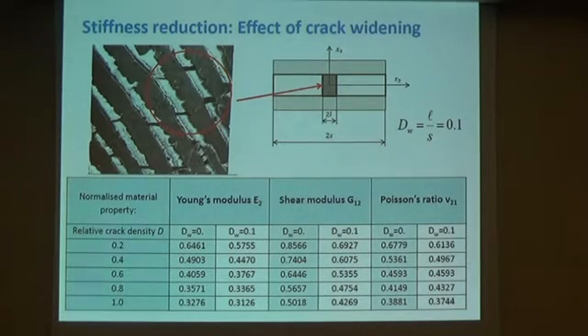How will crack widening contribute to stiffness reduction? Here is a reminder of the photograph with cracks in the ceramic layer, and these are cracks that are quite wide because once a crack formed, the metal layers allow crack edges to move apart. This is a representative segment containing a crack with widening. So it's not a symmetrical section, but a crack of finite width 2L. In this case, crack widening is 10%, and this is the crack widening used in the table.